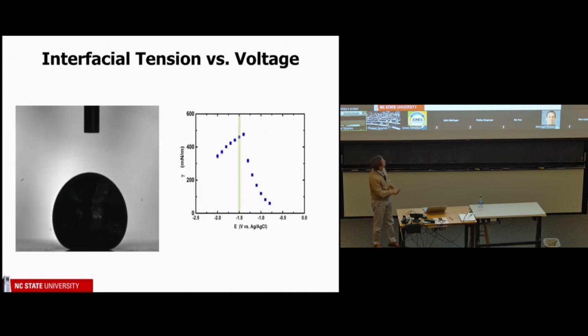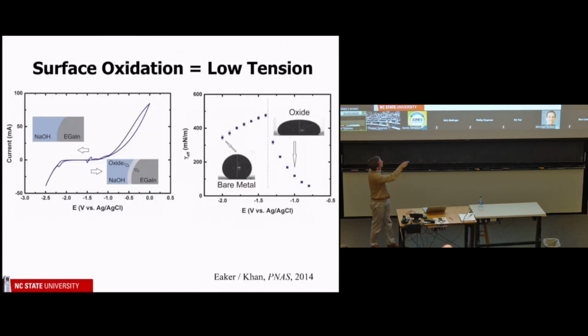You might notice that over here it looks kind of like a parabola. Remember, that's what we expected from the theory from the late 1800s, and it should be a symmetric parabola, but something weird happens right here. It turns out that where that weird behavior occurs, where I've drawn this dotted line, is exactly where the oxide starts to form. We know that because when we measure the current, here's zero current, we see a little bump. That means there's some reaction occurring on the surface. So over here, the anomalous behavior is due to the oxide, and over here, this is classic behavior, kind of boring, but still cool.